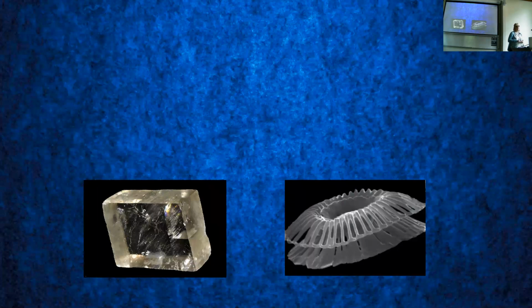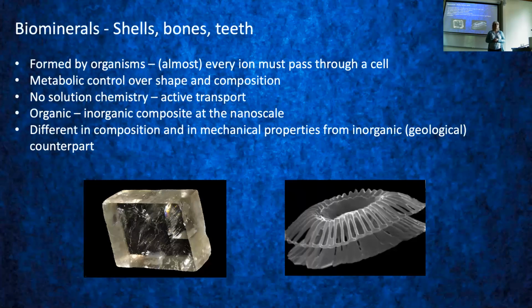They're all really difficult to read in some respects, some more than others, because while they consist of calcium carbonate, calcite, you can see from this coccolith here that the shape is nowhere near what it should be for a geological calcite. They're far away from equilibrium, what we expect in the geological record. And the reason for this is that all these minerals are formed by organisms, which basically means that every single ion has to pass through a living cell.